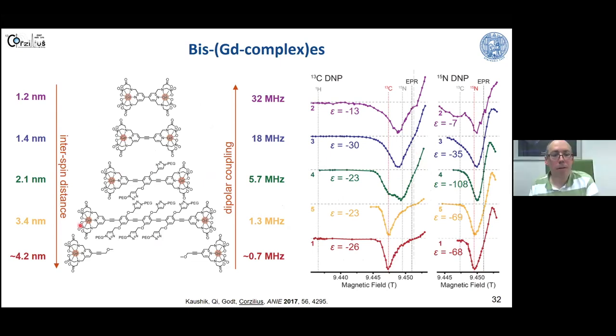So we pursued a similar strategy. We worked together with Adelheid Godt from Bielefeld University, and they are experts in the design and synthesis of such bis complexes. They were able to synthesize this whole series of different complexes with tuned interspin distance, which resulted in a nice series of different intramolecular dipolar couplings. With this, we could show that there is a transition from solid effect at large gadolinium separations to a shared contribution of solid effect and cross effect at some transitional coupling. If we increase the coupling further, the cross effect takes over and dominates the DNP mechanism. We can also show this in 15N, even though it is a little bit less visible here.